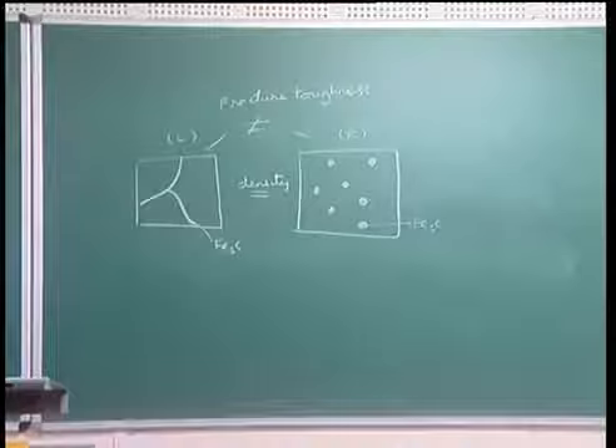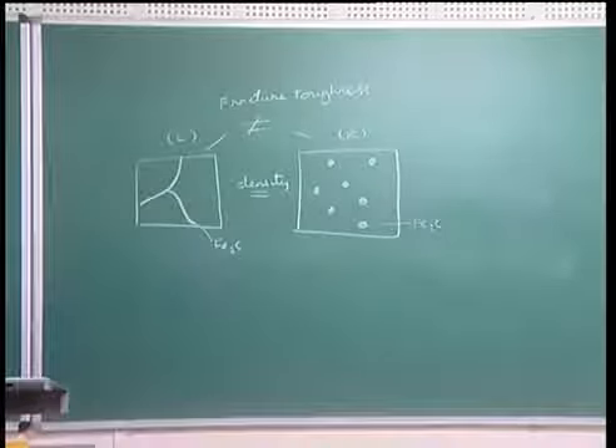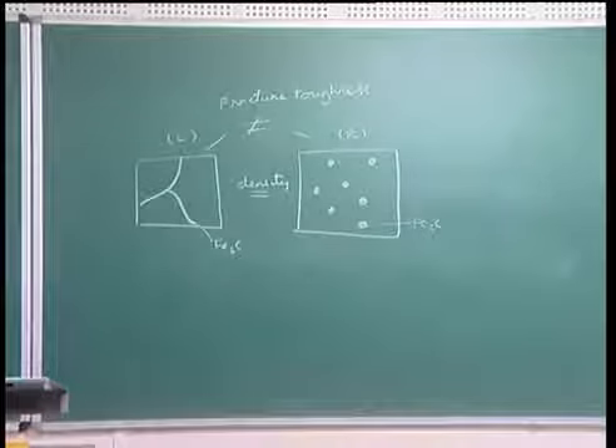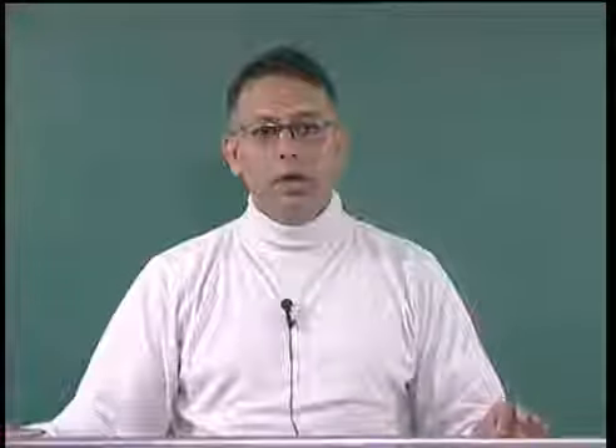And as we shall see, there are quite a few properties which are microstructure dependent, and therefore, I need to worry about my phases and their distribution, and also my defect structure, and also about the residual stress. Again, if the residual stress state is changed between two kinds of distributions, the change in density would be negligible, but a property like impact toughness, as we saw, would change drastically. Therefore, whenever I am talking about a structure sensitive property, it is very important that I worry about all the details which go on to form what we may call a microstructure. During the course of these lectures, we will also evolve a more functional definition of microstructure, which can be used to directly correlate the term with properties.